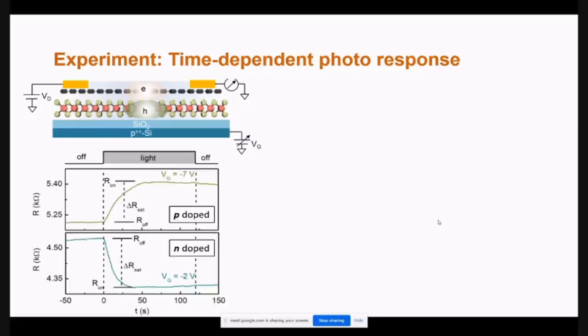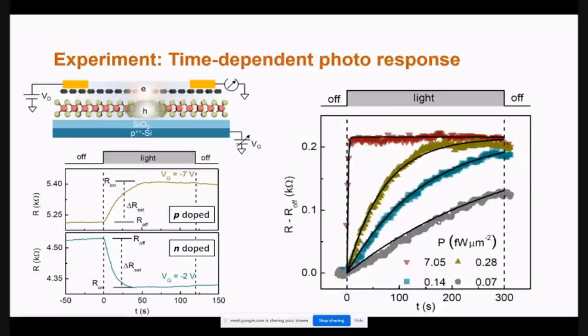But if it is ultra-fast charge transfer, it is not so. Experimentally, you can see that normally this ultra-fast charge transfer happens on the order of a picosecond or less, whereas we see that the change in resistance is actually very slow. You can see when light is switched on, the resistance changes over really tens and hundreds of seconds rather than 10 to the power minus 12 seconds, right? So the question is what is happening, and this change also depends on the power of light that you shine on it.